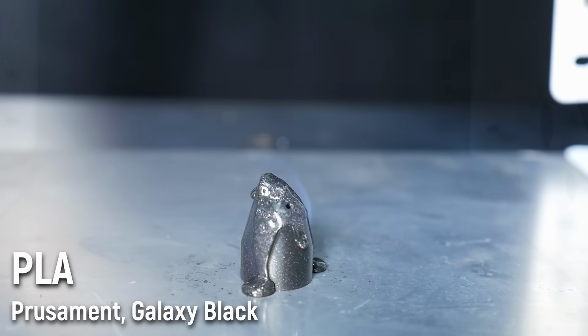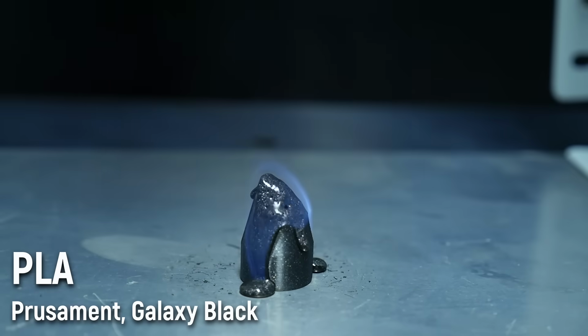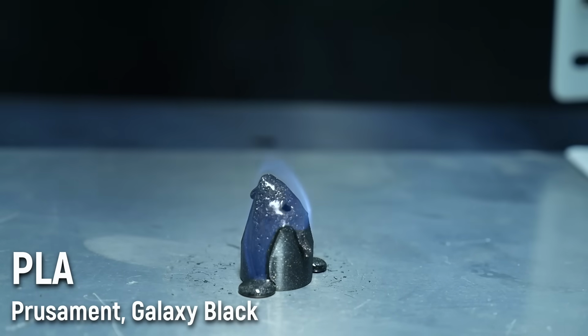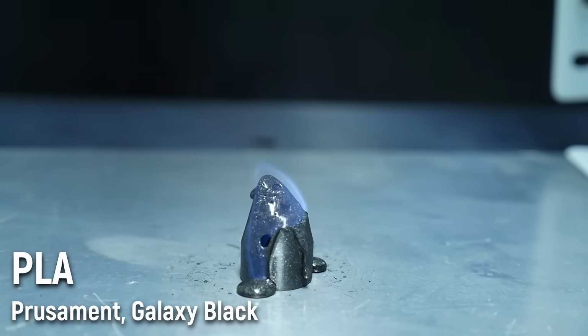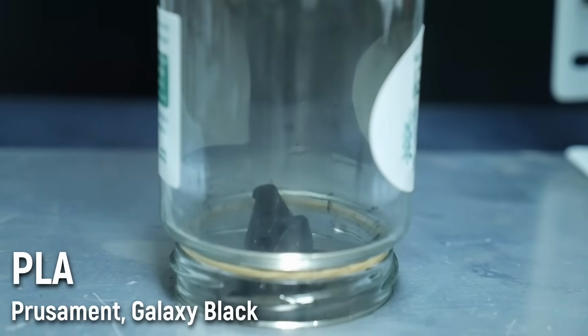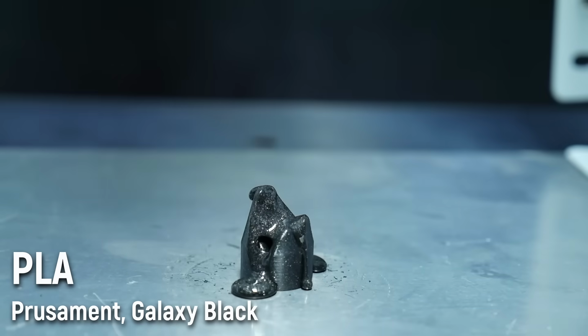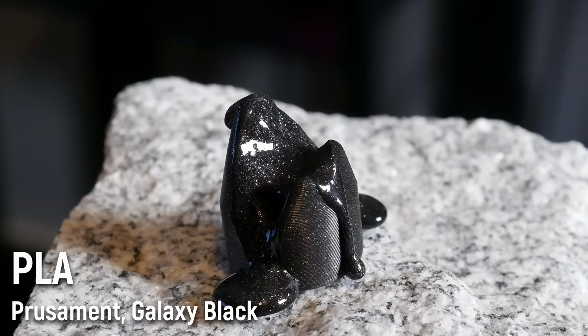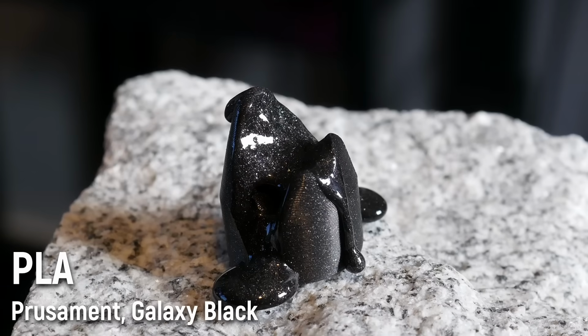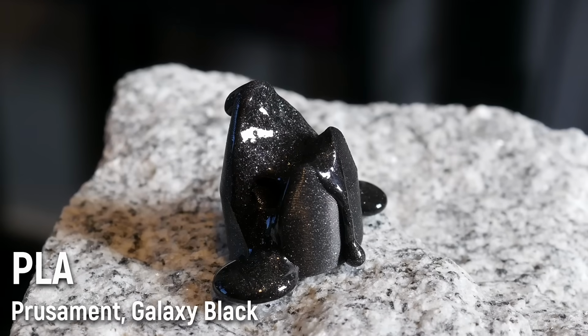I turned down the lights and zoomed in to see what was going on, and I was mesmerized by the sparkly particles swirling around below the blue haze as the print melted like a candle. And once it was extinguished, the print cooled and hardened into a smooth and shiny surface with no charring at all. A very different result for a material that many people treat as the same thing.